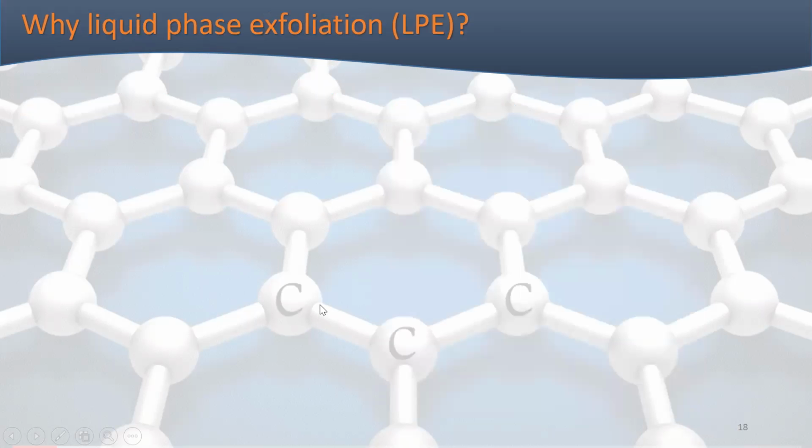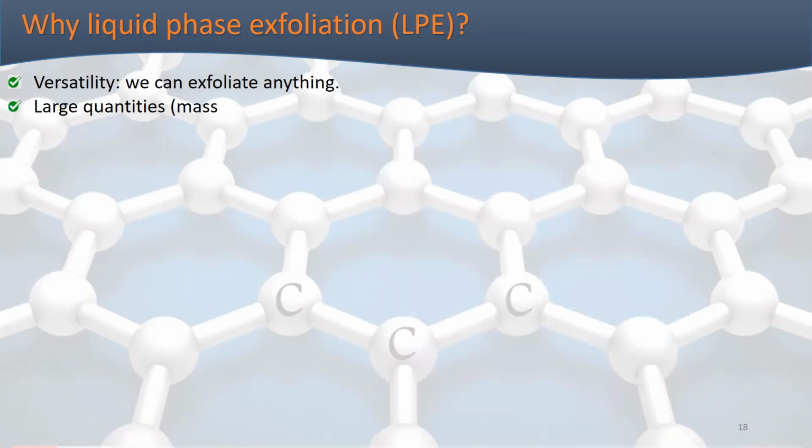Liquid phase exfoliation depends on the exfoliation of natural graphite in organic or aqueous solvent into 2D graphene sheets by means of ultrasound waves, which consist of refraction and compression cycles where the cavitation takes place. This method has been used for scalable graphene production.